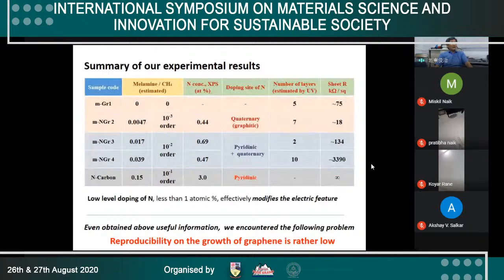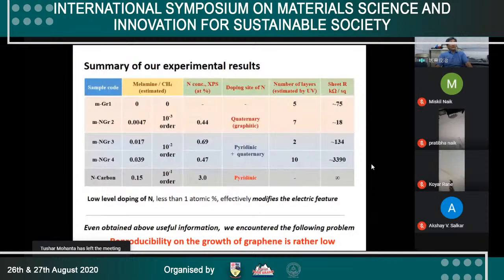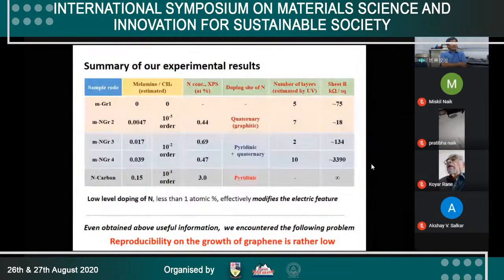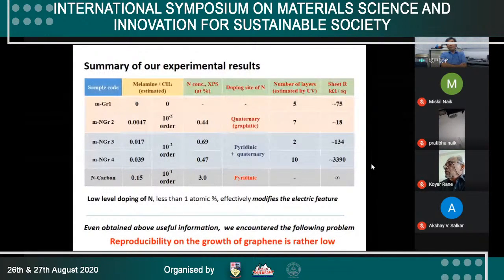So the result is a low level doping of N, less than 1 atomic percent, effectively modifying the electrical features. Of course, that is the interesting result, I think. But from this experiment, even though we obtained useful information, we encountered the following problem. The most serious problem is that the reproducibility of the graphene growth is rather low.